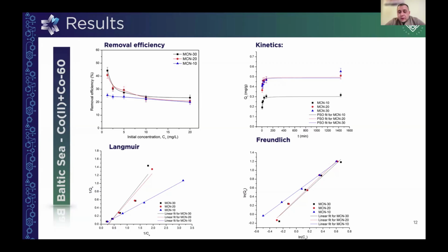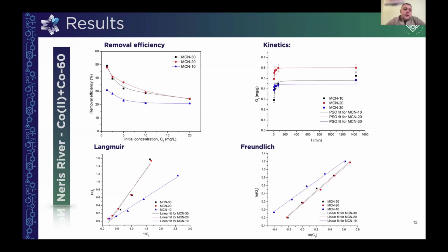So we used different contact times, from 5 minutes till 1 day, 24 hours. And as we can see, about 1 hour and 30 minutes is enough to reach quite a good equilibrium. The second slide is on Neris River samples. Here the removal efficiency is a little bit higher. It's about 50% for MCN 20 and 30 at low concentrations, and for MCN 10 it's higher than 30%. For the kinetics also, we can see that about 1 to 2 hours is enough to reach good results.